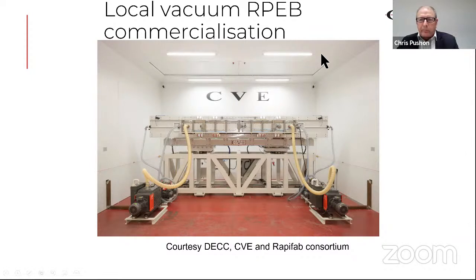What you also notice is we painted the inside of the system shield white. And you'd say, what's the best color to paint a welding system? You wouldn't say it was white, because they get dirty very quickly. But what this illustrates is this still looks the same even after many years of operation. And it's because all the welding fume goes down these pipes into the pump and is trapped by the oil, which is filtered. And then you simply clean the filters or dispose of them. So as a welding environment, it's really quite pleasant. There's no preheat. It's a nice white room and there's no fume.